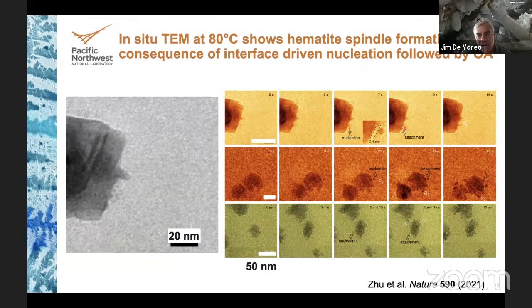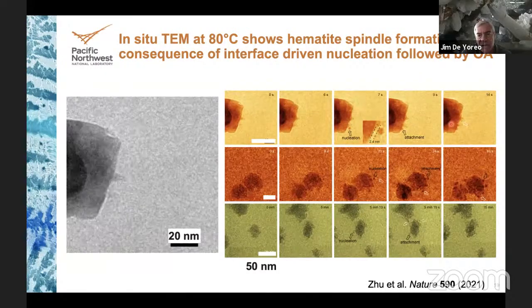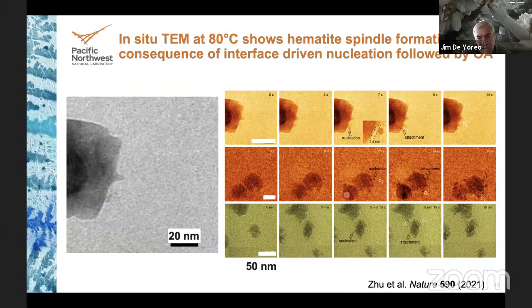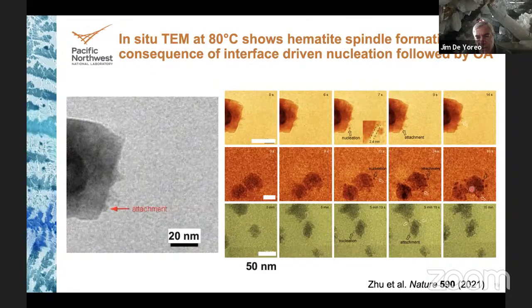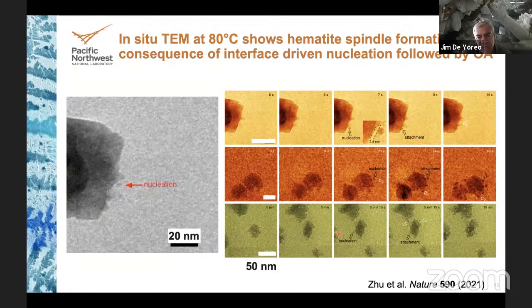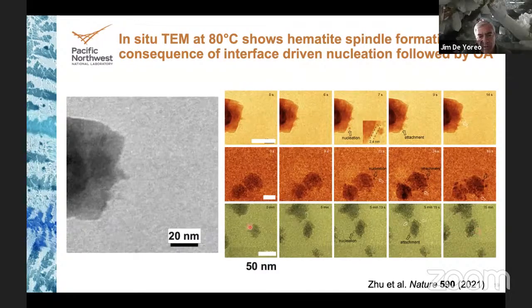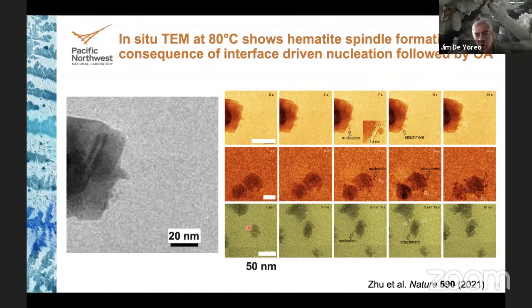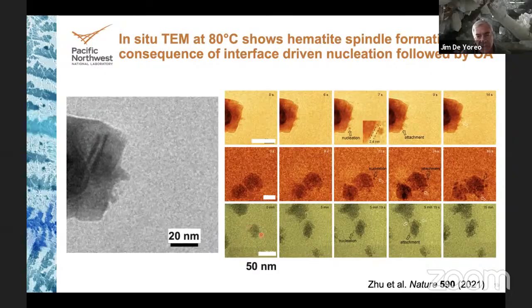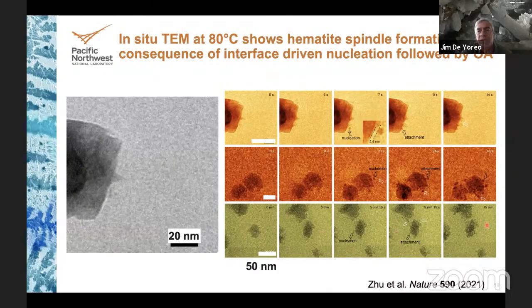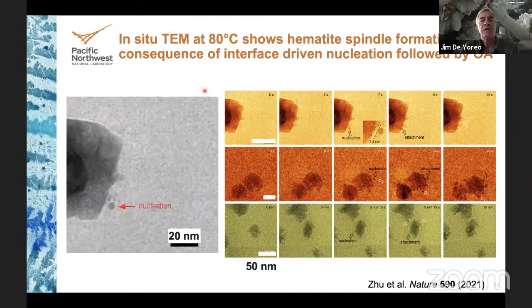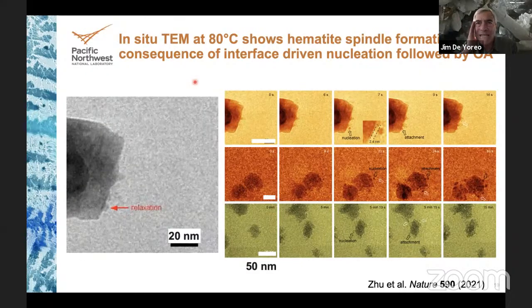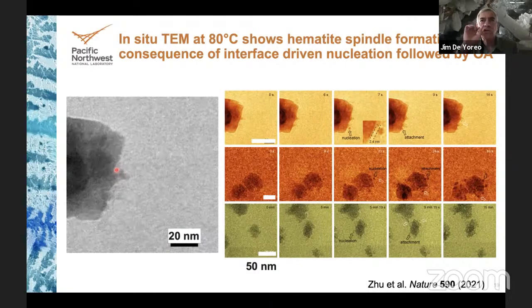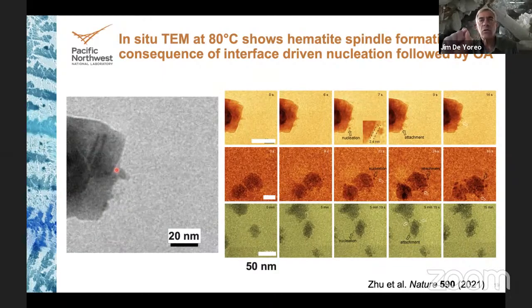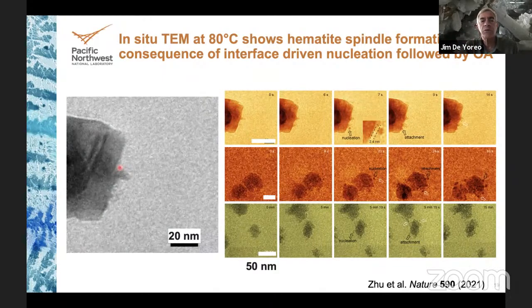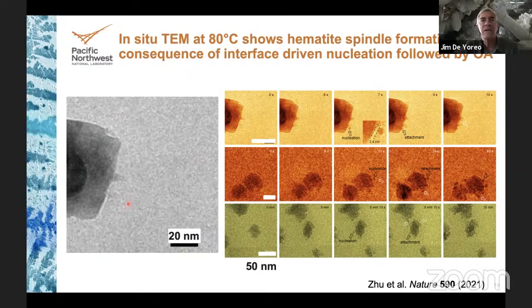You can see that happening here. There's a nucleation event and attachment. Here's another nucleation event and attachment. Here's another set of seeds. You can see the numerous particles forming around them and then attaching. And here's a set of time-lapse images over a much longer period of time where the shutter is closed. It's opened later for some period of time, closed again. And you can see how these seeds then develop into spindles through this process. So the existence of the interface changes the local chemistry in a way that drives all nucleation to happen near the interface, and the particles then